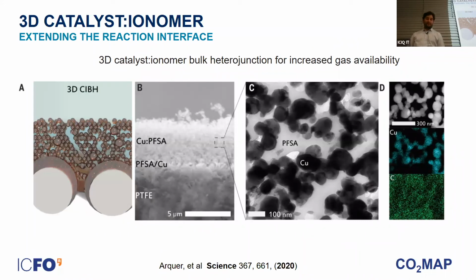Okay, that's a good question. I think this is also something that has not been fully explored yet. This structure was optimized for thousands of hours. So we optimized the loading of copper nanoparticles, the amount of Nafion, and also the solvents. Apparently, when you use one solvent or the other, the way this composite dries is very important. Depending on the ratio of components, the way you spray coat them, the thickness, and the way they self-assemble, everything is different.